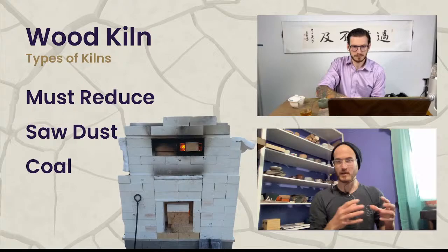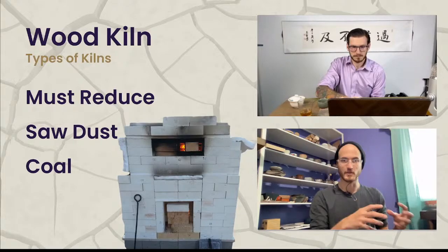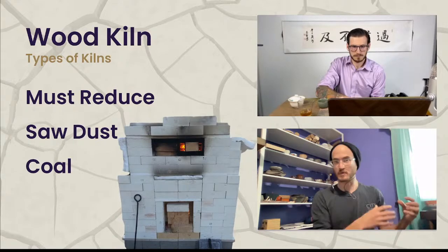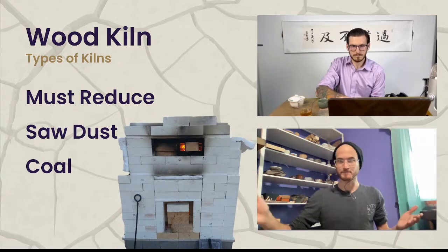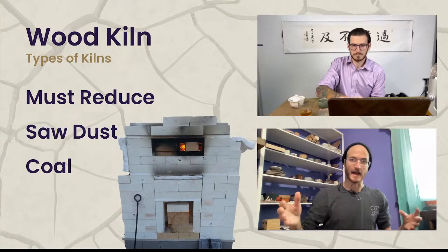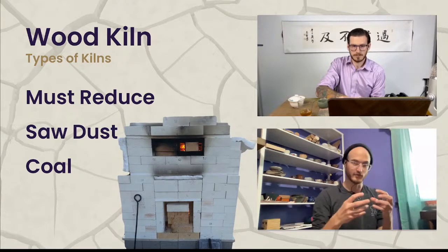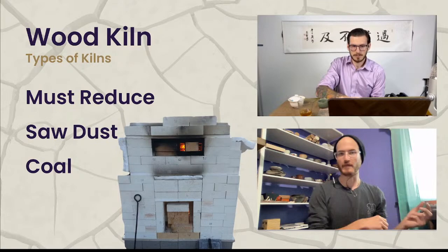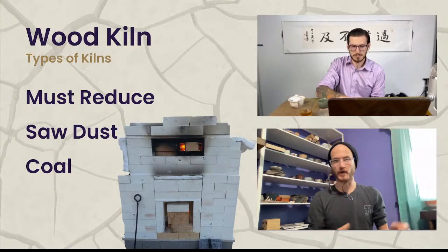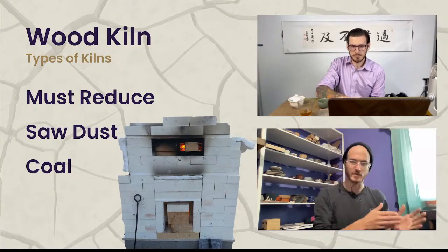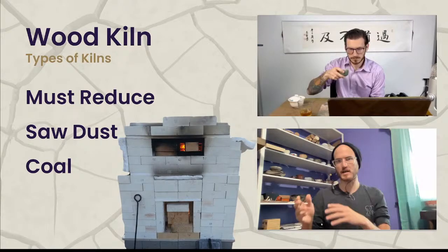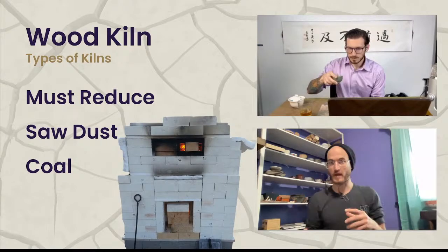And then once all of the organic materials and all the liquid materials burn out of the wood and you just have charcoal, that's when it's sort of creating a clean heat. But as that happens and there's no more raw fuel inside of the wood, you have to stoke more wood. And so wood firing cycle. So it'll be reducing, oxidizing as you stoke, and then wait for it to clear, and then stoke and wait for it to clear.